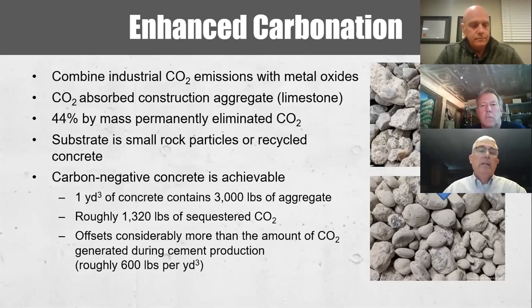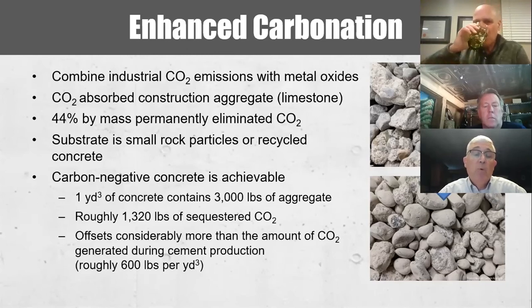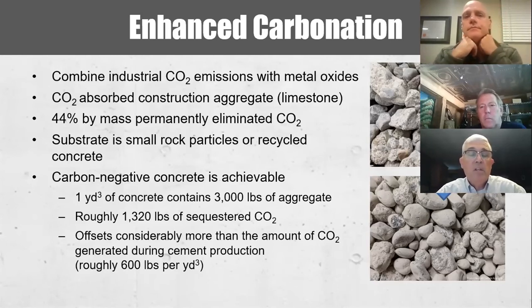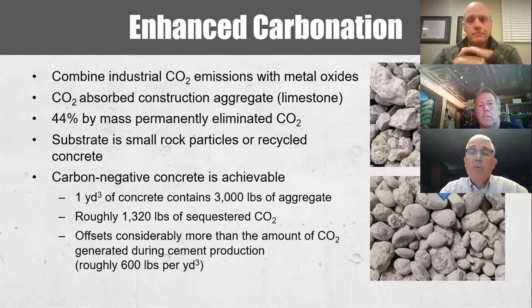mineralized CO2 material. And they claim that carbon negative concrete is achievable, and present this example where if you had 1 yard of concrete that contained 3,000 pounds of aggregate, 44% of that by mass would amount to about 1,300 pounds of mineralized, permanently absorbed CO2 material, which then offsets the roughly 600 pounds of CO2 that was generated during the production of the cement used in that same yard of concrete. So by a factor of 2, you're absorbing far more CO2 than was released during the manufacturing process for the cement in that concrete. So based on this example, carbon negative concrete would be achievable.